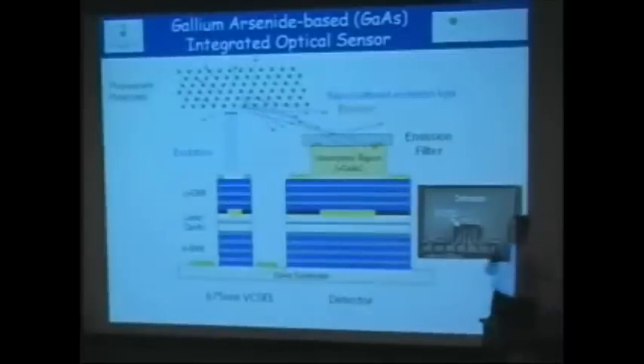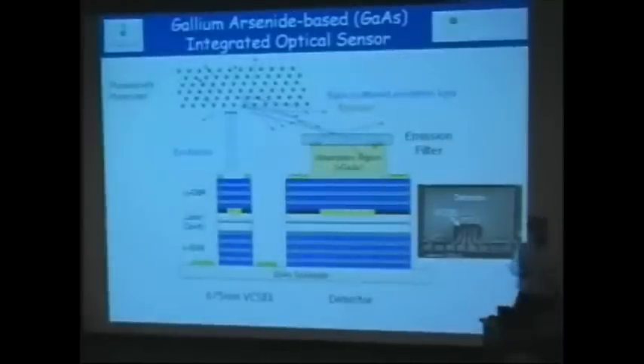So this is a miniaturization of a very classical fluorescence microscope that you would find in many, many labs. Take the whole microscope and shrink it to a 1 millimeter cube. But we keep all the building blocks as we do that. We chose to work with this dye, as you can see here in the diagram. The excitation that we chose is around the peak, which is around 675 nanometers. So this is where we optimize the laser light to be. And we create an emission that goes well above 700 nanometers.